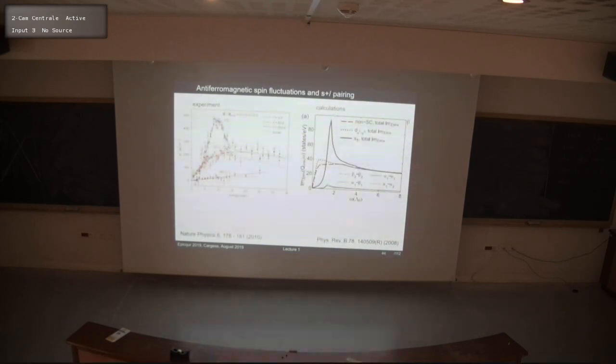And this type of scattering will give a small broad feature in the spin susceptibility. So now this is being used as a test to check what will be the pairing mechanism and what will be the response in neutron diffraction. These are the calculations I showed you earlier. It shows this very strong resonance at the Q vector associated with the nesting vector, which promotes this S plus minus pairing as relevant for superconductivity in these materials.